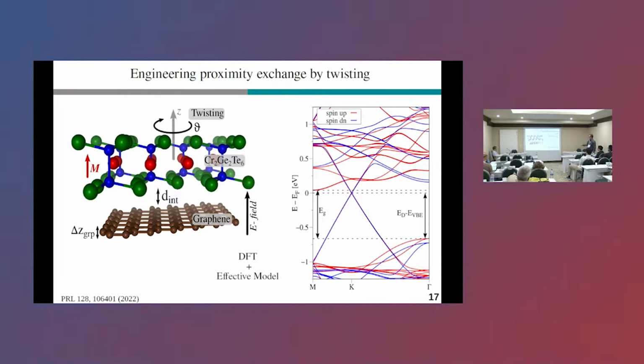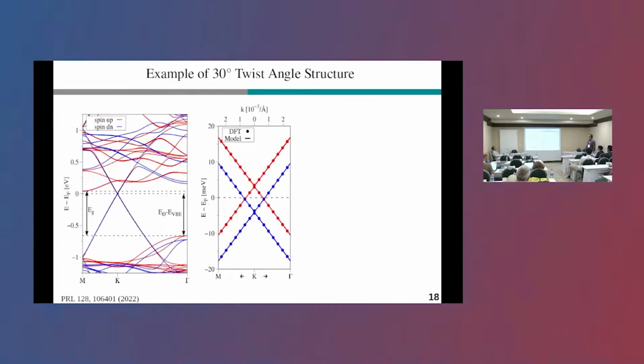And the situation roughly always looks like this. So the Dirac states are nicely preserved within the band gap of the CGT. And now let me discuss on a specific example what is going on, which is the 30-degree twist angle structure. So the overall band structure we have already seen. The two different colors correspond to spin up and spin down. And if you then zoom in to the Dirac states for this 30-degree structure, you will find that the spin down bands are pushed to lower energies compared to spin up.